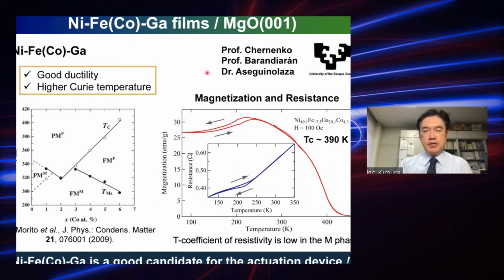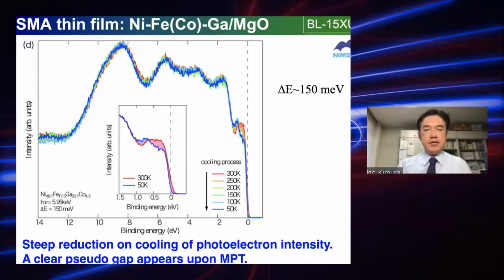So actually we have worked with hard X-ray photoemission and X-ray magnetic circular dichroism for this alloy in order to get insight into the underlying mechanism of this phase transition. As you can see, the Martensitic phase transition occurs near 200 Kelvin. Here are photoemission spectra as a function of temperature ranging from 300 Kelvin down to 50 Kelvin. The horizontal axis is the binding energy with respect to the Fermi energy, which is located at 0, and the vertical axis is the intensity of photoelectrons.